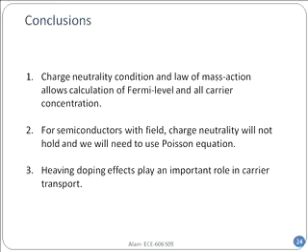If we had one, then this condition of charge neutrality, and the law of mass action, np equal to n_i squared, all have to be thrown out of the window. Not completely thrown out, but modified. And then we'll have to use something called the Poisson equation instead of the simple equation we had to calculate electron and hole density. It is slightly more general, and we'll see that.